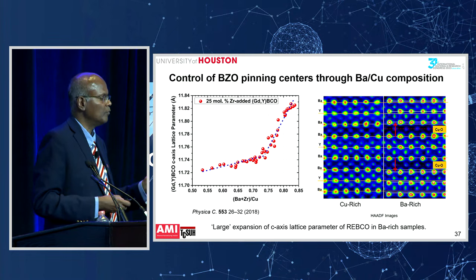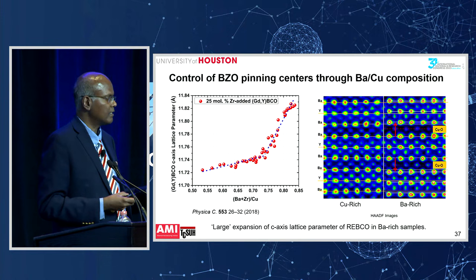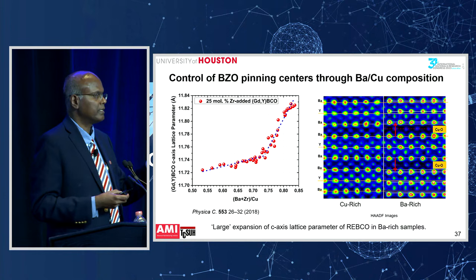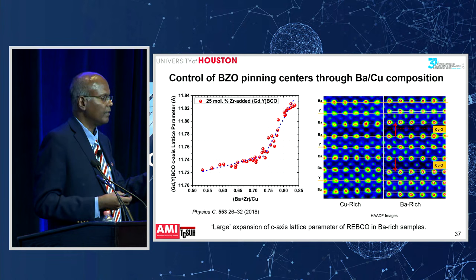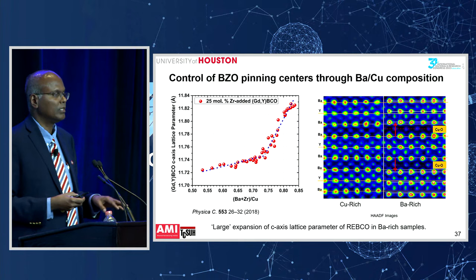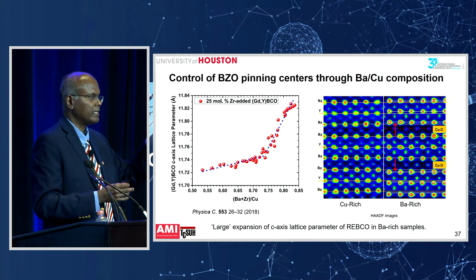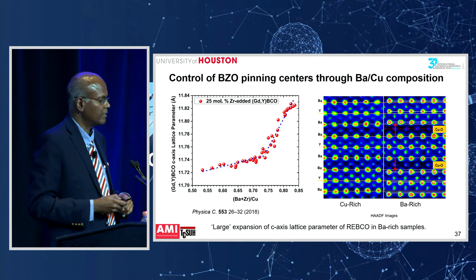So what I'm showing in the chart there is that on the left-hand side, we have increased the barium content in the film, right? What I'm showing is barium plus zirconium over copper, which is really mostly increasing the barium content in the film. You can see there is an increase in the lattice parameter of the film, of the superconducting film. And actually, you can see in the high resolution TEM images on the right-hand side, as you go from copper-rich to barium-rich film, the c-axis lattice parameter keeps increasing, right? You can see the effect of that in a couple of slides. So that's what happens as you increase the barium content.